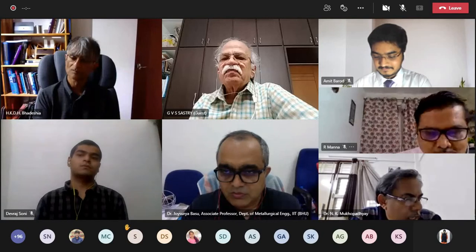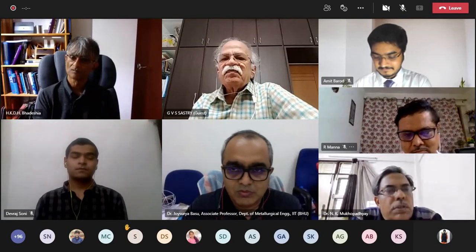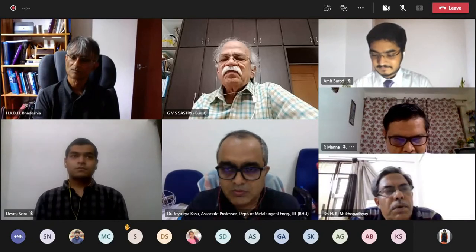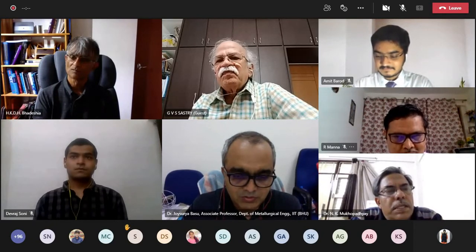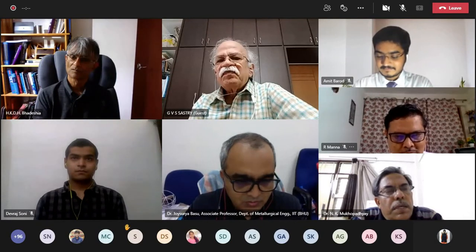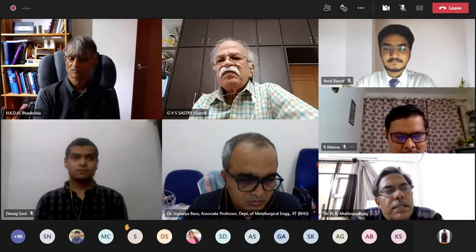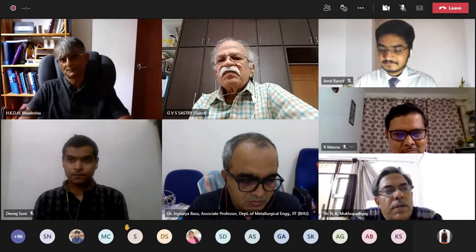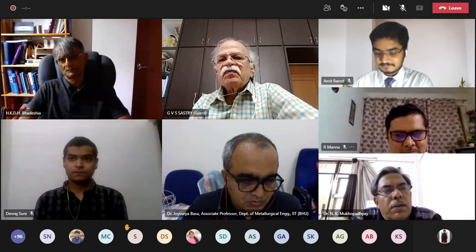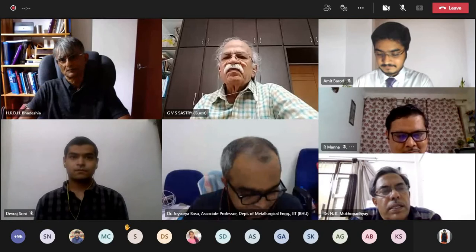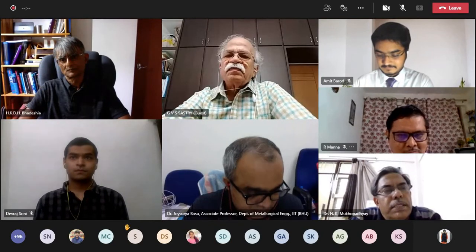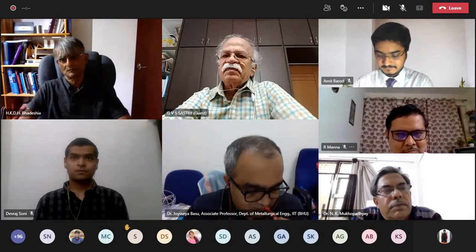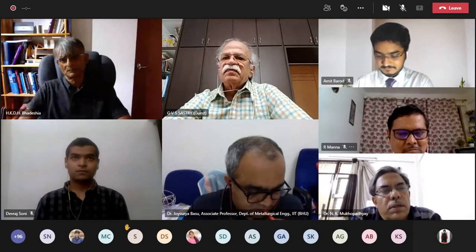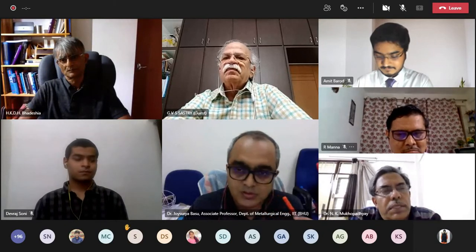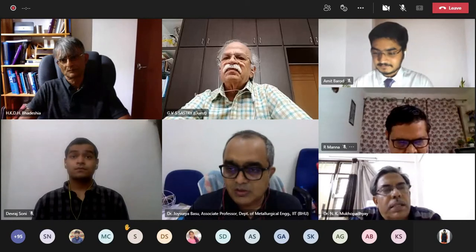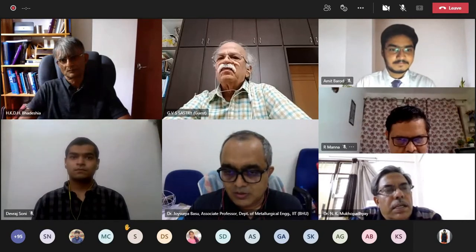That is number one. And number two, as you have given a series of lectures on high entropy alloys, people do talk about high entropy steel, especially one group. And recently we are also trying to tackle some work on high entropy steel, taking the expertise of Dr. Manna as well. Iron, nickel, chromium is common, and then we put in manganese and aluminium, just to reduce the density, and then see what kind of microstructure you get, B2 meaning ordered BCC and disordered BCC, very similar to a superalloy kind of structure, and whether that can withstand very high temperature applications.